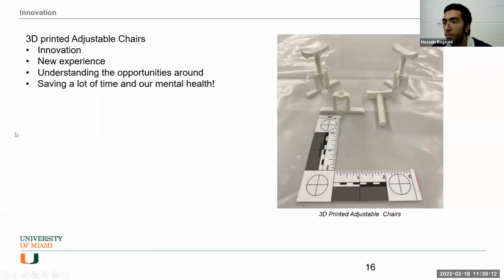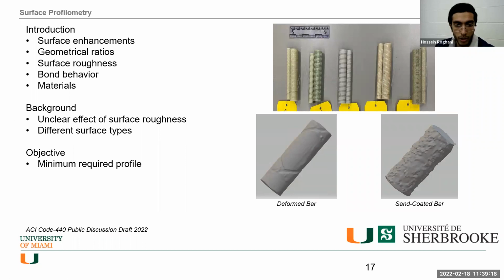So I want to wrap up the previous study about the shrinkage, and I'm going to the second project, which we have recently started working on, which is the surface profilometry of the FRP rebars, the non-metallic reinforcement, which is a collaborative research with the University of Sherbrooke in Canada. And this research is the second leg of my dissertation and is characterization of the FRP rebar surface profile and find the relationship between the geometrical ratios, surface roughness, and finally the bond behavior, which is an important concern in reinforced concrete. We have 5 different surface profiles.